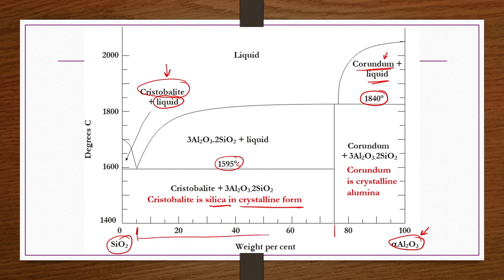But if you have any percentage of these two, let us say 10 to 75% of alumina in silica, and then apply higher temperatures, you can see that irrespective of the composition in this range, you get mullite. Along with that there would also be some cristobalite, which is nothing but crystalline silica. It is possible up to 1595 degrees centigrade.